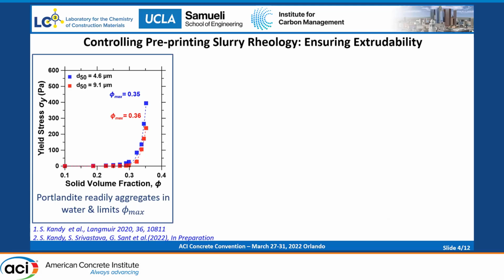This is basically because portlandite is slightly soluble in water, and because of this, the suspensions have a high pH and high ionic strength, and this ionic strength screens the electrostatic charges. So the portlandite particles are attractive in nature or slightly weakly repulsive. When you put it in water, it gets aggregated, and this aggregation limits the maximum volume fraction that we can achieve in these suspensions.